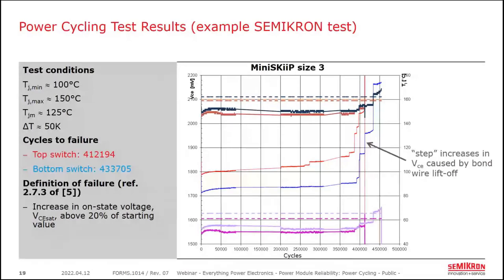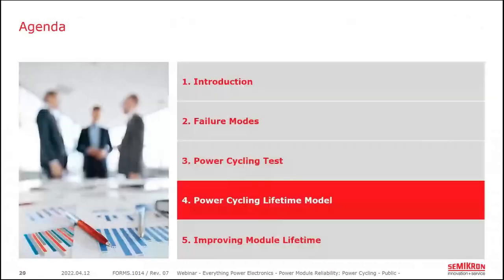You can see for this test, we started at 1.8 volts, and then after more than 400,000 cycles, the voltage drop has increased to over 2.1 volts. And so it's been a failure of the test. We've just defined our power cycling test. And now we're going to look at the actual model that we can use to predict lifetime.